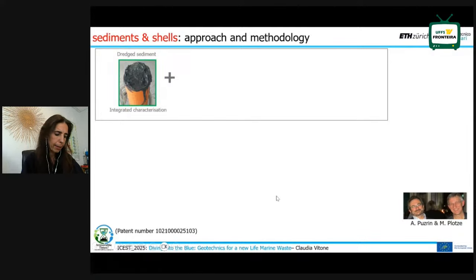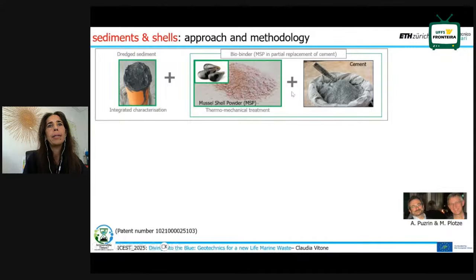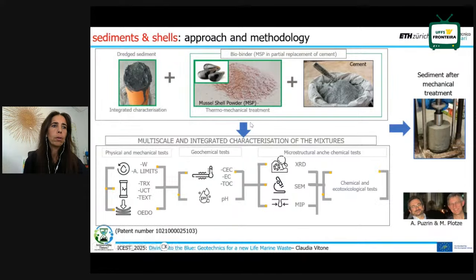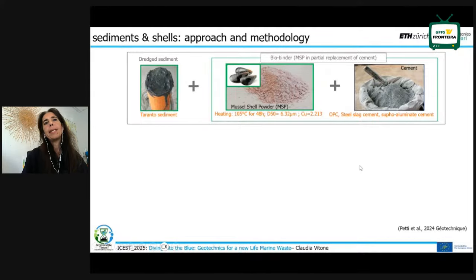So the idea was essentially to mix the sediment, after their integrated, multi-scale characterization, with a biobinder that we developed by mixing the cement with this mussel shell powder after a thermomechanical treatment. So essentially, this mussel shell powder allows us to reduce the content of cement. We tested these solutions a lot, we patented the methodology, and we realized a lot of tests to obtain this stabilized material. Some details about the mussel shell powder: heating at 100 degrees for 48 hours, the D50 is 6 microns, and essentially we could check the efficiency of the solution with different cements.